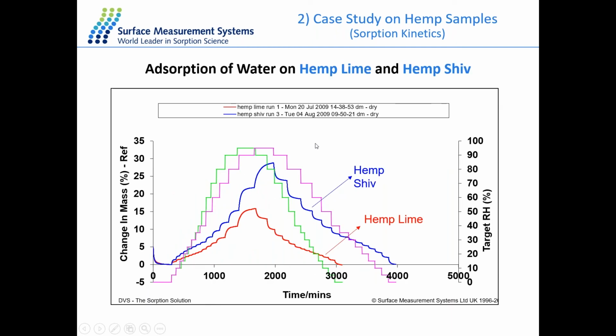And we also did some study on the hemp samples with the water sorption of both hemp shiv sample and also hemp lime composite. So the hemp shiv, the blue line, is a kind of woody core of the hemp plant that has very low density due to its high porosity, and it can absorb a very large amount of water in the pores. And in the case of the red line, lime is a kind of binder that will bond with the hemp shiv to improve the thermal insulation, as well as the vapor permeability, for use as a construction material. So from the DVS data, we can see that the hemp shiv sample has much faster kinetics than the hemp lime sample.